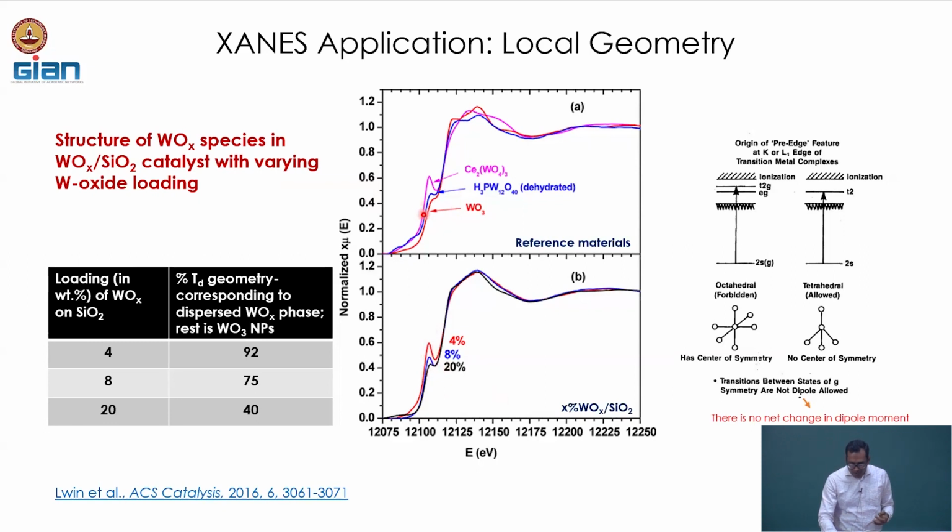And of course, I can do a simple linear interpolation kind of thing: for a pure substance with a WO4 structure versus a substance where there is 100% WO6, what is the area under such a peak, and based on that, what I found from my sample, I can actually back calculate the percentage of WO4 in tetrahedral state versus the percentage of WO6 in octahedral configuration, and that is what has been shown